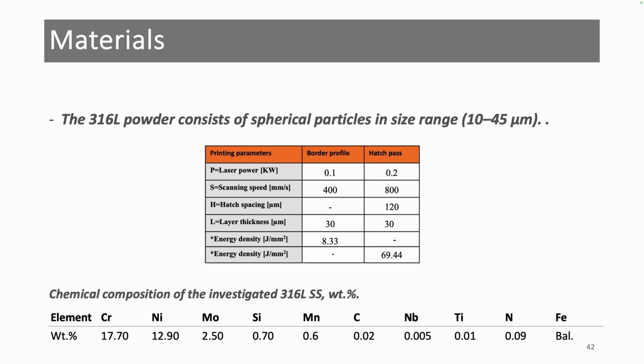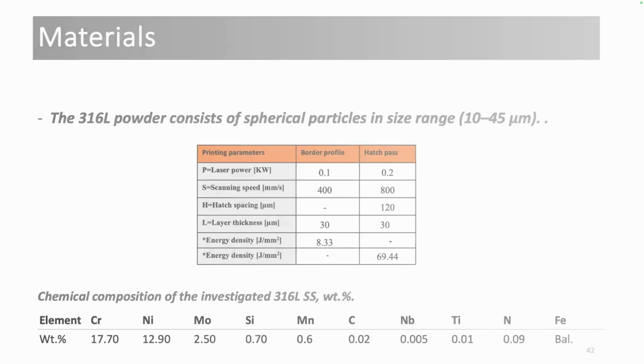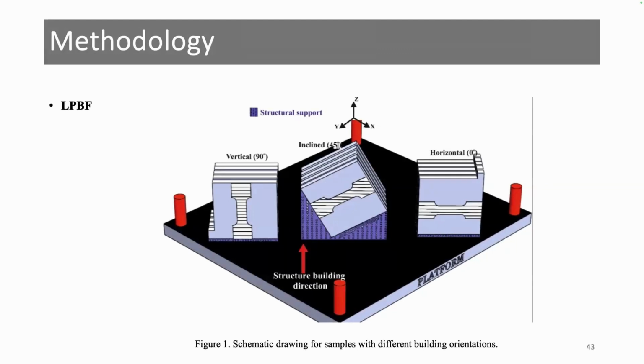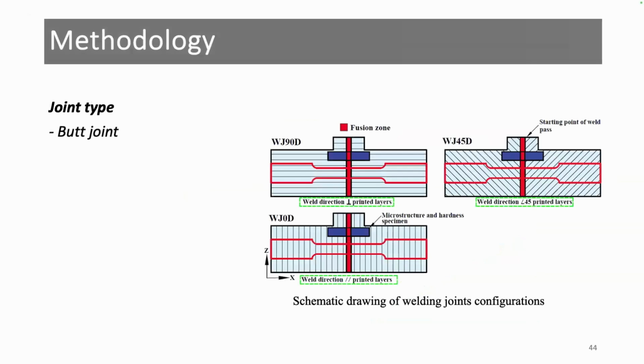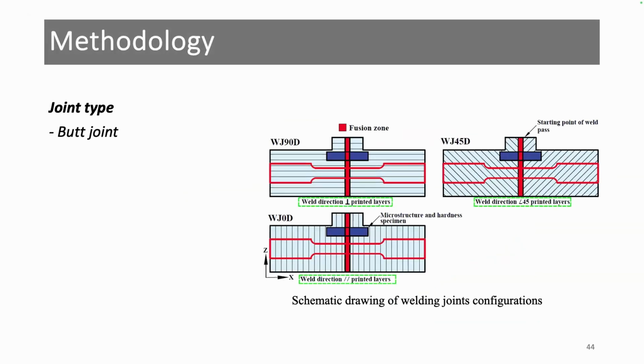The material, the 316 stainless steel, consists of spherical particles with size ranging between 10 and 45 micrometers. We use this printing parameter for the base metals. And here is the chemical composition of the powder. Regarding the methodology, we performed three different printing orientations of the material: 90, 45, and 0 degrees. The welding methodology implies butt joints. And here is the relationship between the building orientation and the welding.